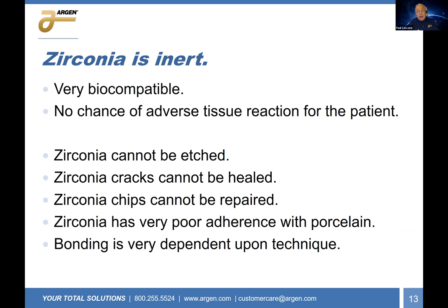It has very poor adherence with porcelain. And that was one of the main reasons why monolithic zirconia took off so fast, because everyone was really tired of the chipping of the porcelain in vivo. And then bonding is very dependent on the technique. The material used is very important, but also right now it's very unreliable compared to what dental porcelain or the lithium disilicates are.